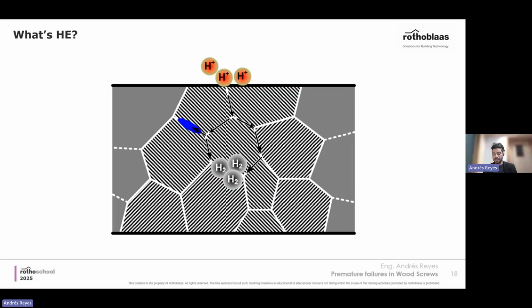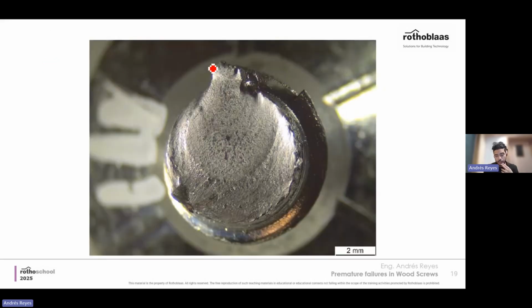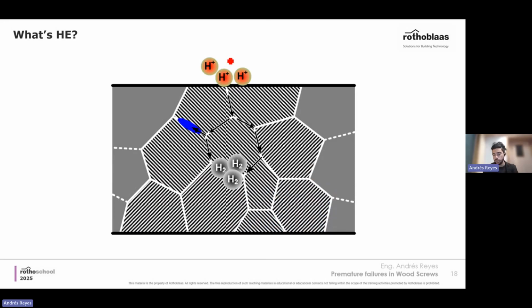How does this happen? In many processes, during manufacturing and also when the screw is in service. Hydrogen from outside can migrate from the exterior into the structure of the fastener, and then it can accumulate in the grain edges and in some parts of the structure. Then when the screw is put in tension, or any type of tension force, the hydrogen will also try to move to reach the surface. In this movement, the hydrogen will assist the creation of cracks in the structure of the screw. That's what we call hydrogen-assisted cracks, HACs.